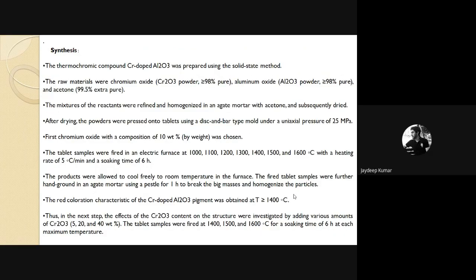Also, the threshold of the color transition temperature can be varied depending upon the concentration. If we take 5% of chromium oxide and 95% of alumina, that turns from red to green at approximately 250 degrees centigrade. And if we take 10% chromium oxide and 90% alumina, then that turns red to green at a range of 400 to 450. So this is a good example: depending upon our concentration as well as temperature, we can get whatever we want. At any temperature we can take a particular concentration, and at a particular concentration we can take any temperature.